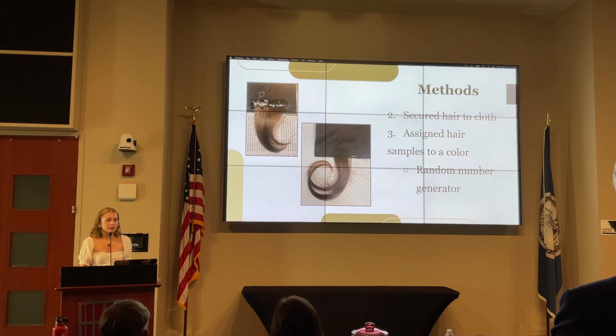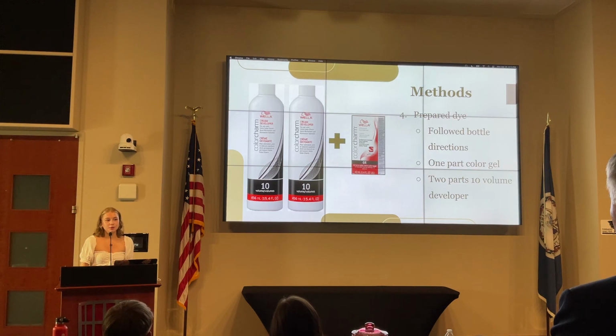I then numbered the hair samples 1 through 28 and used a random number generator to assign them to a color group. Once the color groups had been finalized, I followed the manufacturer's instructions and mixed a 1-part color gel to 2-part developer mixture. I used a 10-volume developer because it oxidizes the least amount of pigment from the hair. Because the focus of my study was on color-specific damage from the dye, I wanted to reduce the likelihood of damage from the developer itself.